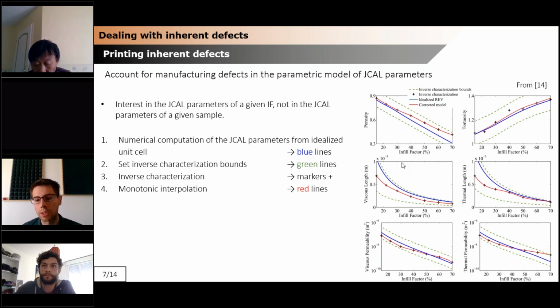And what is nice with these results is that experimentally, we see that, for instance, the porosity is higher than numerically, and that it is what was predicted by the simulation of the defects. So we can get the acoustic parameters, and they are coherent with what we expected from the simulation of the defects.